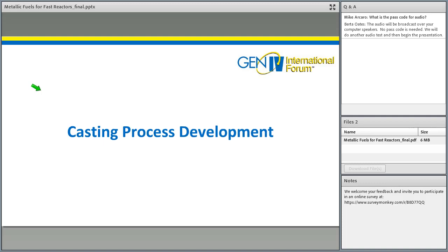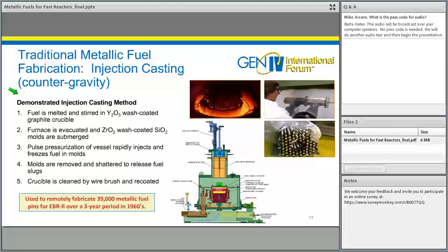Now getting into a little bit more of the technical details, starting with fabrication, specifically casting. Casting is the approach that has historically been used to fabricate metallic fuels, and specifically counter-gravity injection casting. And so the way this is performed is we typically use a graphite crucible. Now, molten metallic fuel is not compatible with graphite, so the graphite crucible has to be coated, typically with a yttria wash. So a coated crucible is used to heat the metallic fuel charge up to a molten state,